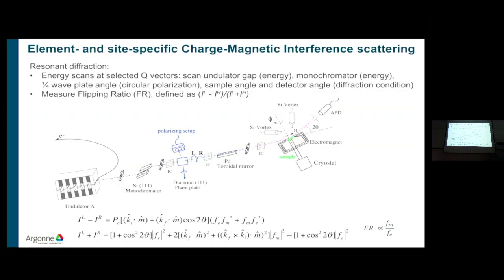We have the undulator. We can tune the gap to change the energy. We can scan the angle of the monochromator to pick, and as we scan through a resonance, we have this phase retarder or quarter wave plate to convert the light from linear to circular, and we can flip the helicity with this phase plate. And we can measure this charge magnetic interference scattering, and especially the ratio of the difference divided by the sum by flipping this helicity and calculating this